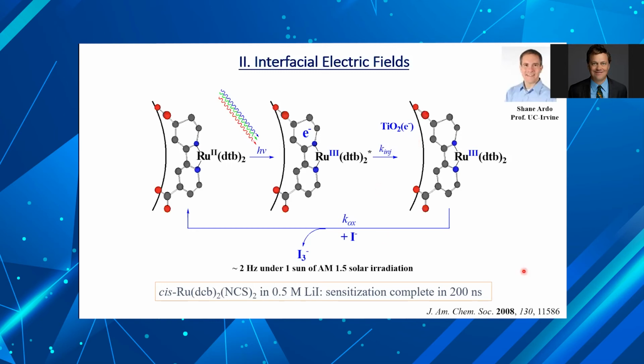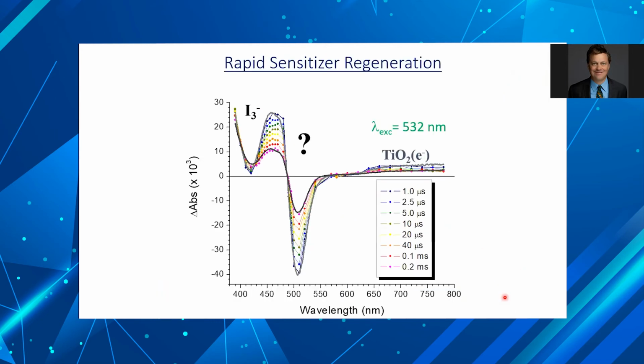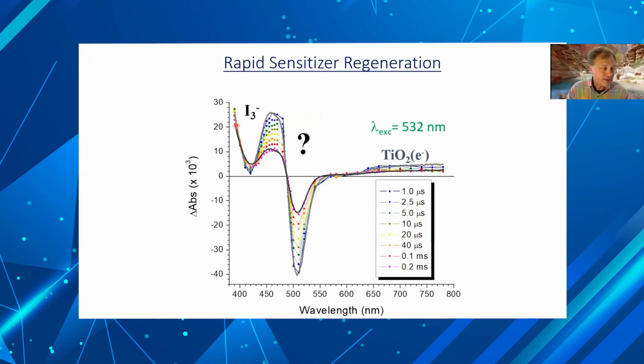And Shane, over 10 years ago now, showed that that wasn't the case. He was doing regeneration studies, looking at transient absorption kinetics. He expected at these delayed times to see the injected electron and the oxidized iodide. Instead, he got this first derivative looking spectrum. When he first discovered it, it was a very, very small effect, and then he found some dyes that he could optimize the effect for. So it was very careful work on Shane's part that allowed this discovery.